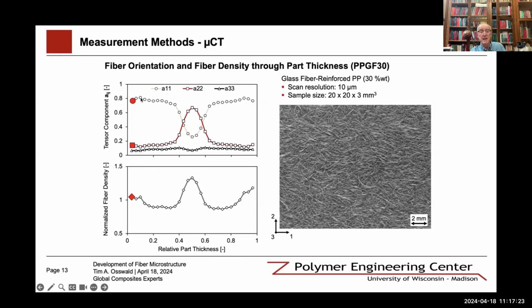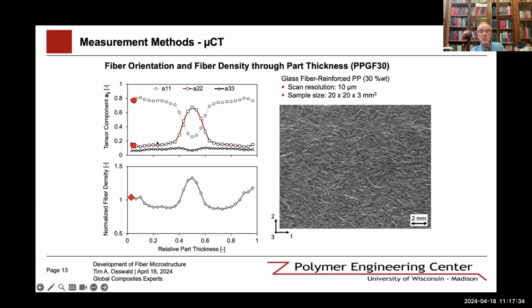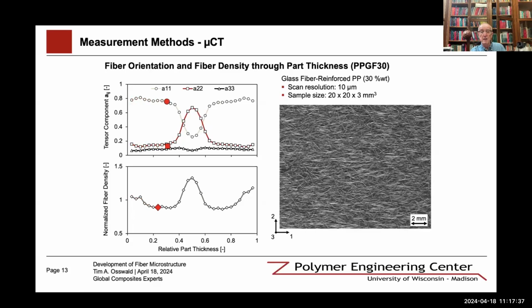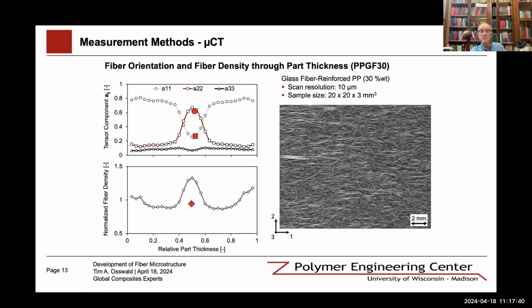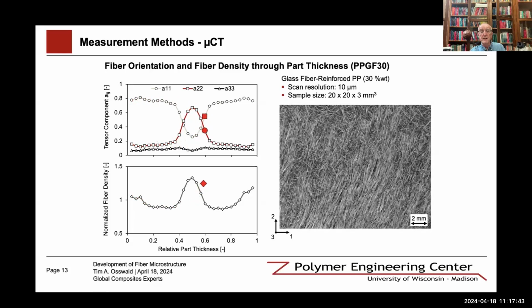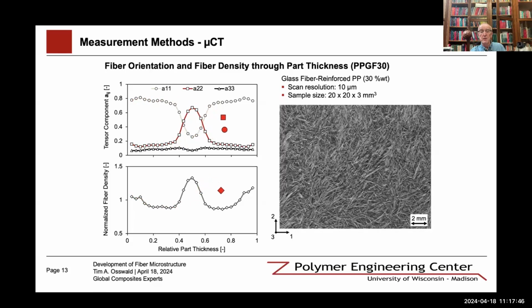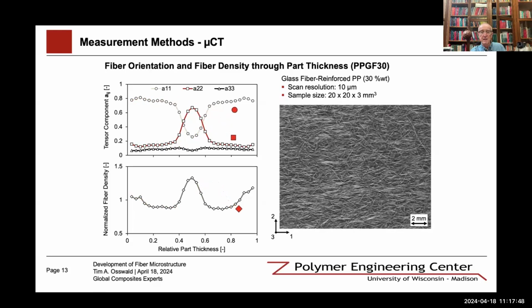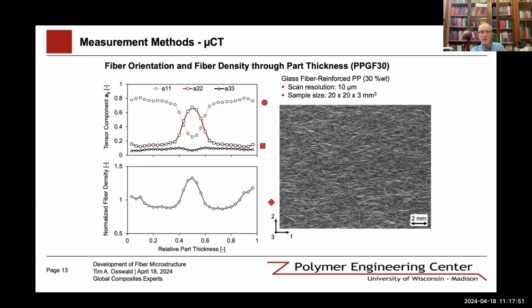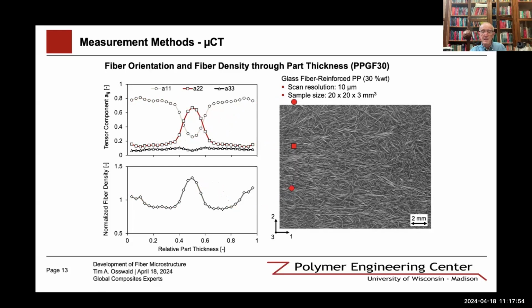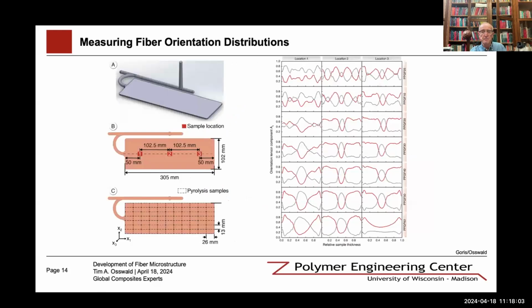You can see that in the A11. A11 is the direction of flow. A22 is the direction perpendicular to the flow. So these are the orientation tensors across the thickness. So we can see, if we travel along the thickness of the part, how the fibers orient in the direction perpendicular to the flow. And I think my dots are flying around a little bit more crazy. But you can see the orientation, how it changes, but also how the density of the fiber becomes higher in the center of the part.